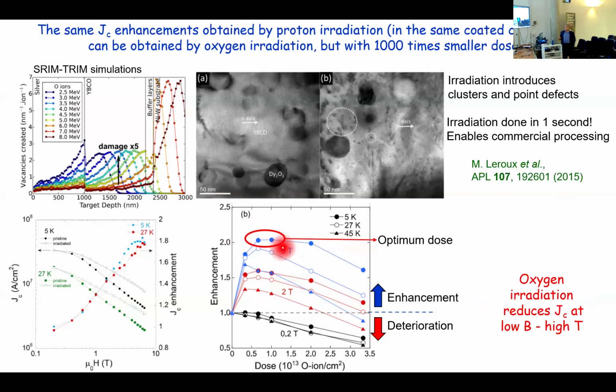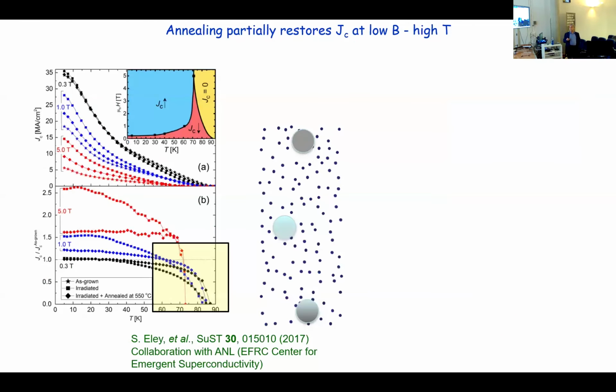And then at high fields, at lower fields, we never see an improvement, and we saw a deterioration from the first dose, even from very low doses. So oxygen irradiation increases Jc over most of the phase diagram and reduces it at low fields and high temperatures. And we explored that in detail.